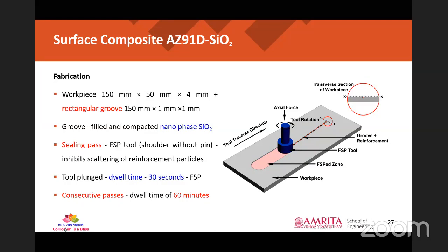Okay. Then what we have done is we have plunged the tool inside. Then after a dwell time of 30 seconds, FSP trials were carried out. The consecutive passes were done. For example, if I'm going to do one pass or two pass, it was done after a period of 60 minutes. So let's see the macro structure results over here.